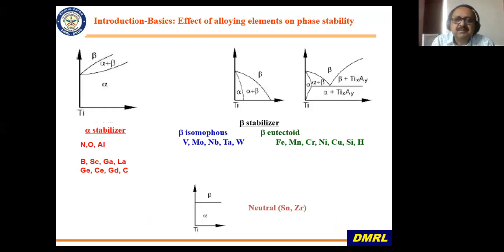Now, as far as alloying elements are concerned, as you all know, titanium exists in two crystal structures. First is alpha, which is a hexagonal close-packed structure, and the beta, which is a BCC structure. And the alloying elements that stabilize either of these phases are known as either alpha stabilizers or beta stabilizers. Now, if you look at alpha stabilizers, nitrogen, oxygen, aluminium are the most important ones, and there are others also like carbon, boron, lanthanum, etc.